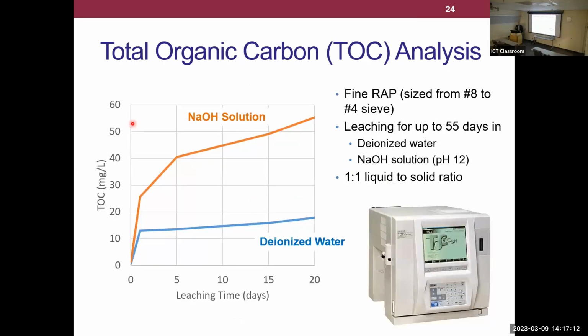The first thing we did was just a simple proof of concept. We took some RAP and soaked some of it in an NaOH solution, sodium hydroxide. Again, pore solution is a high pH. It has sodium, it has potassium, it has hydroxyl ions and some other stuff. For simplicity, we just used NaOH as an analog, much easier to work with. So we did a pH 12 NaOH solution. We soaked the RAP in that, and then we also soaked it in water.